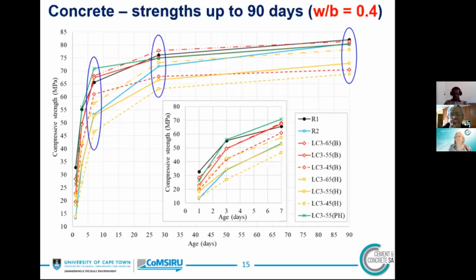Now, talking about the early age gain of strength of these mixes, you can see that the mixes with 0.55 and 0.65 clinker factor, especially the LC3 mixes with B clay and PH clay, gain strength similar to or better than the reference mix R1. That indicates that the LC3 system is much better because the binders react strongly during the first few days compared to most binary mixes, where the main problem is the slow gain of strength at the early ages.